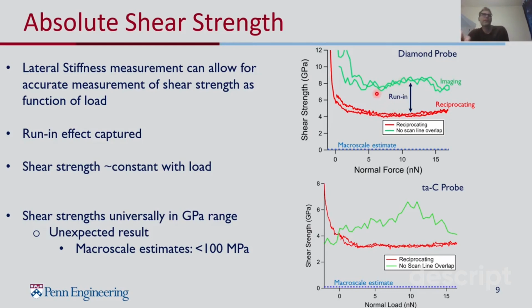But the final thing to note is the actual absolute value of these shear strengths. They're astronomical. They're in the gigapascal range. And just as a frame of reference, the hardness of the silicon-doped DLC is around 10 gigapascals. So the interfacial shear strength is of the same order of magnitude as the hardness of the starting material. And that sounds like it's high friction, and it is high friction.